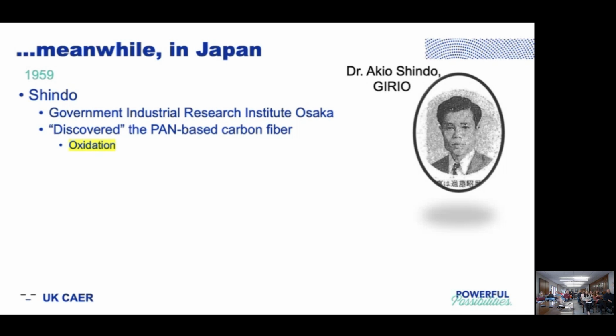This gave us, for the first time, insight into the role of oxygen on the very front end heating process. In the latter case, he consumed all the oxygen and didn't arrive at a nice oxidized intermediate, and the resultant carbon fibers were quite brittle.